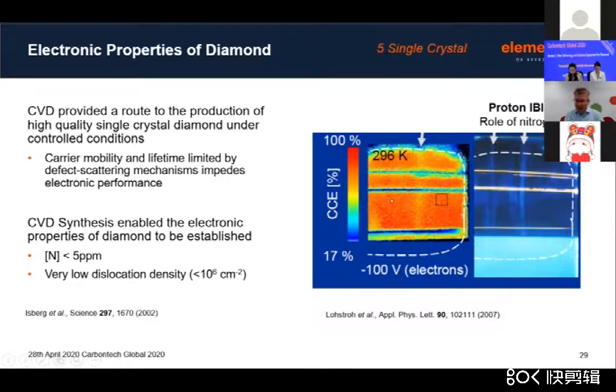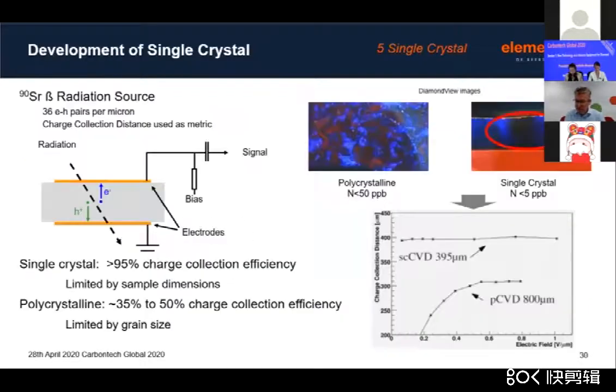And as you can see here, this is what's called proton IBIC. You're looking at the current imaging, and you're seeing 100% charge collection efficiency in the areas where there is no nitrogen, and in the areas where it's even 20 parts per billion of nitrogen, the charge collection efficiency falls right off. And that was very important to being able to go back to our original experiment of taking one of these solid-state ionization devices with a calibrated source, and what you find is single crystal diamond can have a charge collection distance that is only limited by the size of the sample itself. It rapidly saturates at very low voltages and therefore is constant. So there's very little trapping in this material.